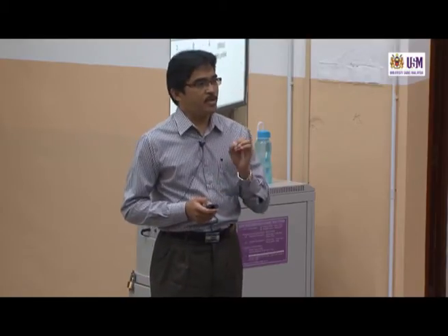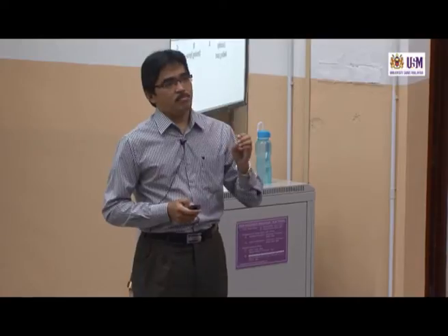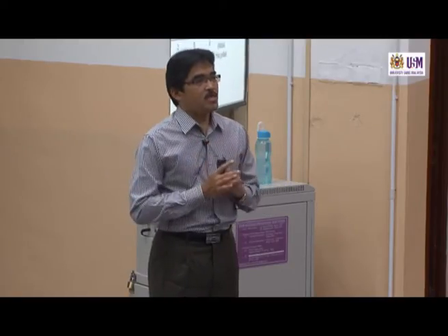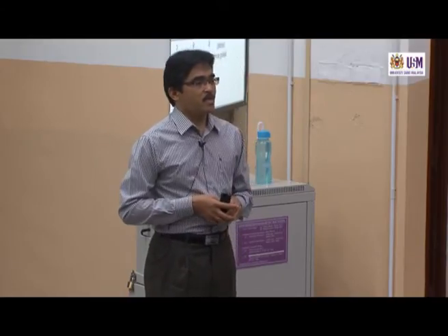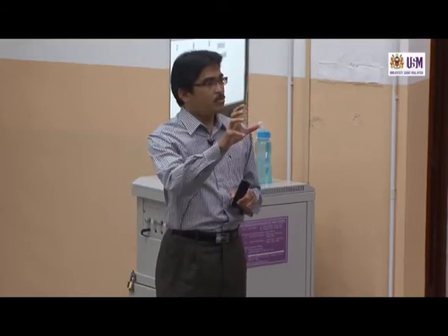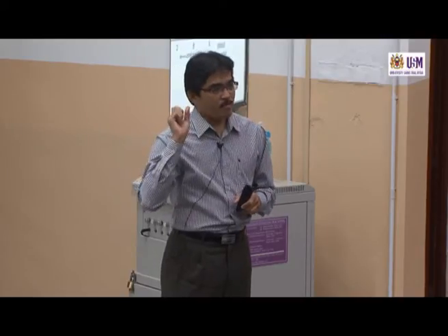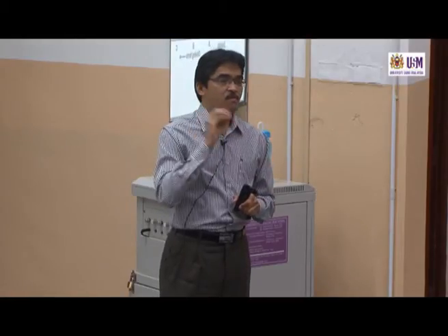We can manipulate the temperature, we can manipulate the rate of cooling. We can manipulate the degree of supersaturation. Remember the delta C, the C_ss minus C_s. Because this is what we call manipulating or controlling the driving force. Remember this keyword, driving force, daya penggerak. What drives the nucleation? What makes the nucleation fast or slow? It's about the driving force.